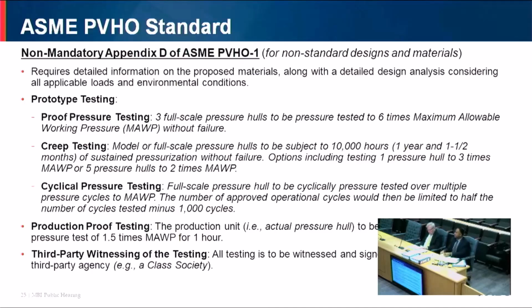So under creep testing, what is creep? Creep basically means, under sustained hydrostatic loading, does the pressure hull deform? Okay, that is creep. So for creep testing, you will use model or full-scale pressure hulls, and they are subjected to 10,000 hours of sustained pressurization without failure. So 10,000 hours basically means 1 year and 1.5 months. So you will pressurize the hull and maintain the pressure for 1 year and 1.5 months, and then you check if the hull has deformed or it has failed by creep. Okay. So the options available include you test 1 pressure hull to 3 times MAWP, or you test 5 pressure hulls to 2 times MAWP.